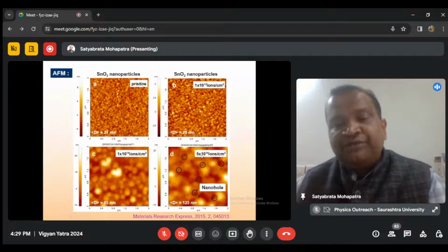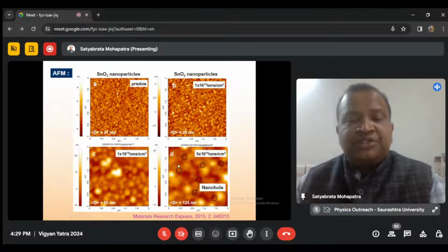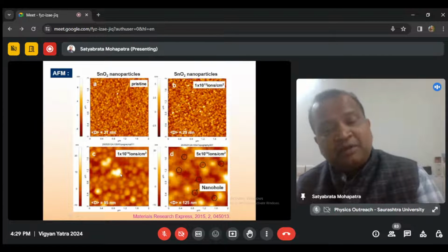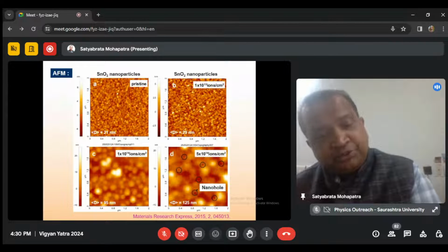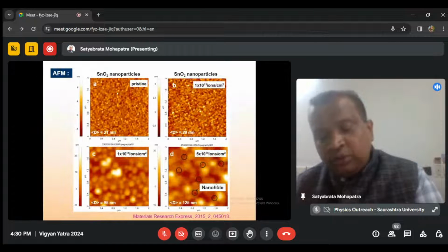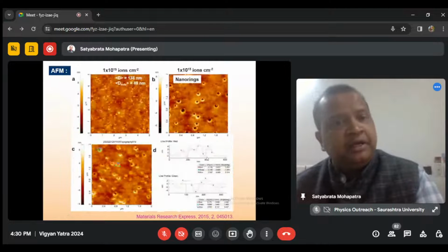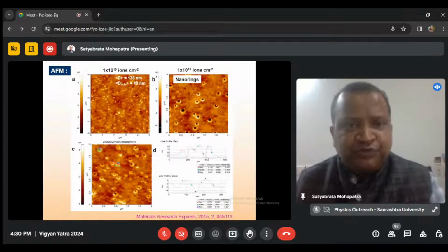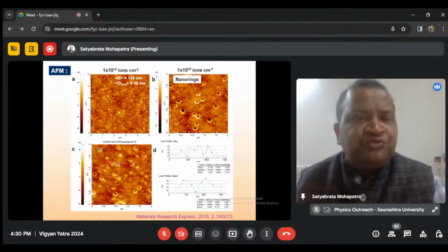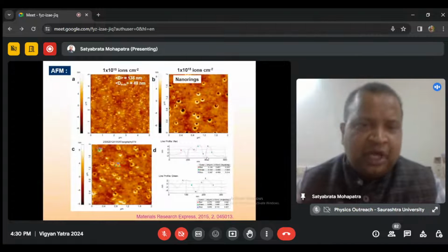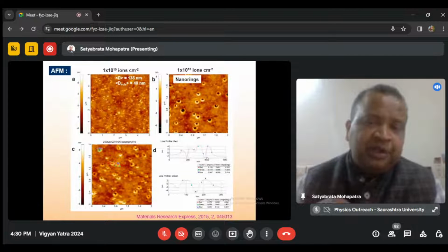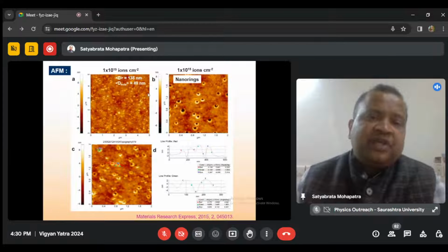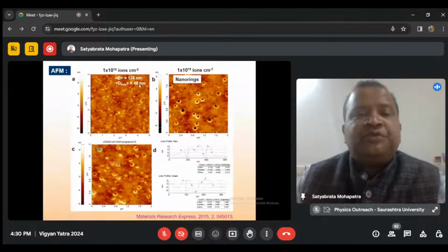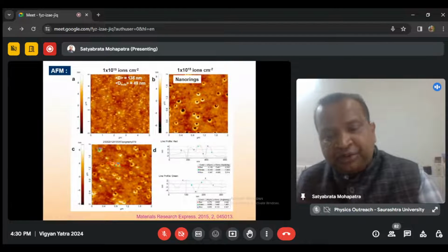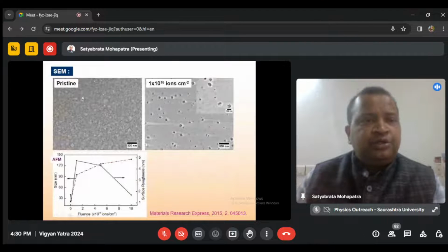However, beyond that, at a fluence of 5 × 10^14 ions per centimeter square, nanoholes started emerging on these nanostructures. The nanostructured film started developing nanoholes. Of course, these big structures are still there and they're growing bigger, to around 125 nanometer. If we increase the fluence further, you can see these beautiful nanorings distributed almost uniformly across the film. This is shown over 5 by 5 microns, but they are everywhere. So we can engineer these nanorings of tin oxide. These are basically holes decorated with nanoparticles of tin oxide around them, and the outer size is 138 nanometer, with a hole size of 49 nanometer. So you can see that beautiful nanorings have developed, and this is again confirmed from the SEM image.